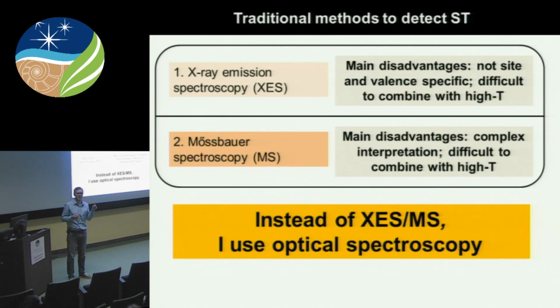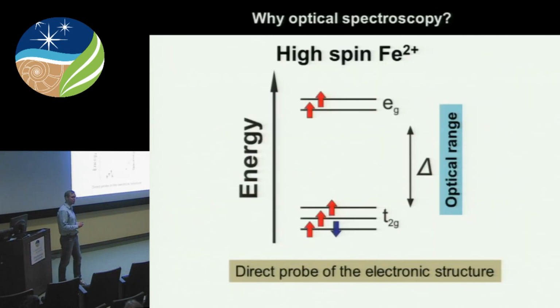Also, X-ray emission spectroscopy is not a site and valence specific technique, which means that if you have a mineral which has several different iron configurations, valence or coordination configurations, you won't be able to distinguish between the spin transition at these sites with the X-ray emission spectroscopy technique. Mossbauer spectroscopy is a site and valence specific method. However, the interpretation of Mossbauer spectra is very complex, and in other words, we don't have good references for how low spin Fe2+ and Fe3+ iron should look in Mossbauer spectra for crystal chemically complicated minerals. And instead, I propose to use optical spectroscopy.